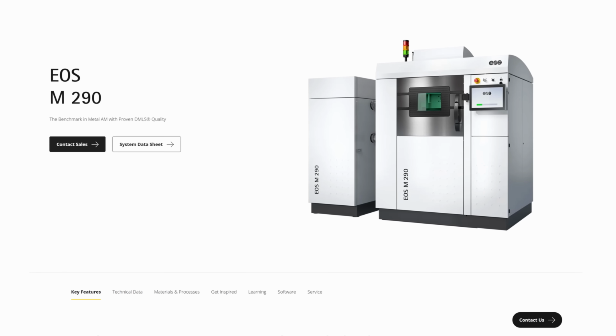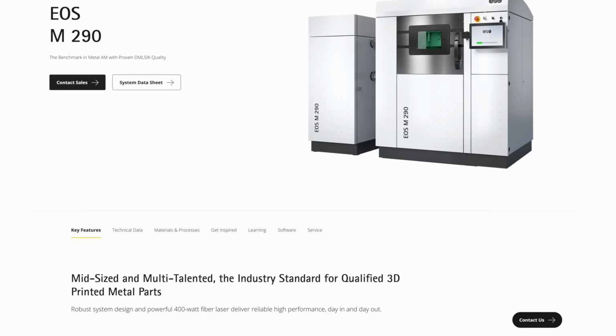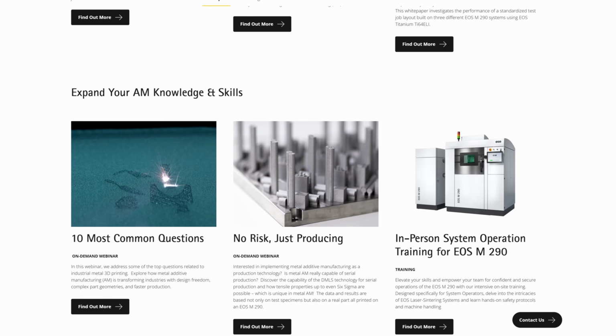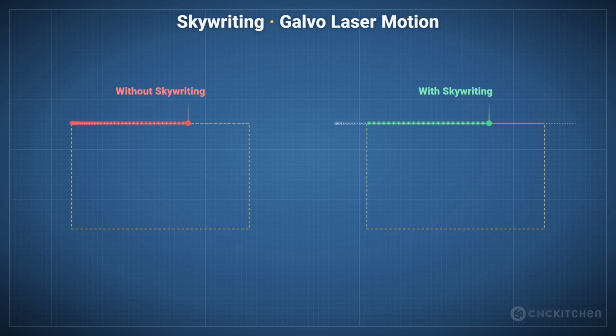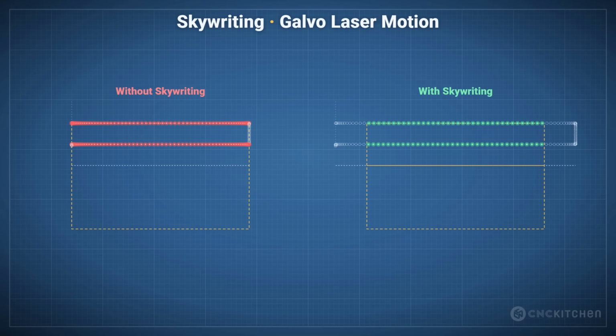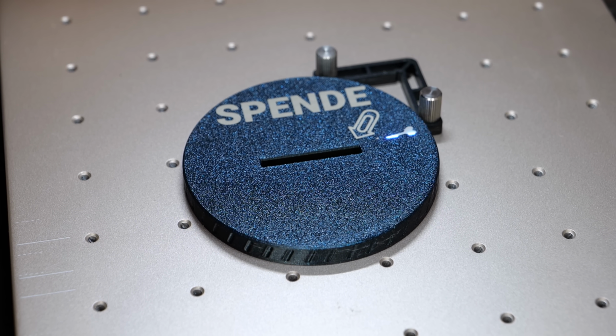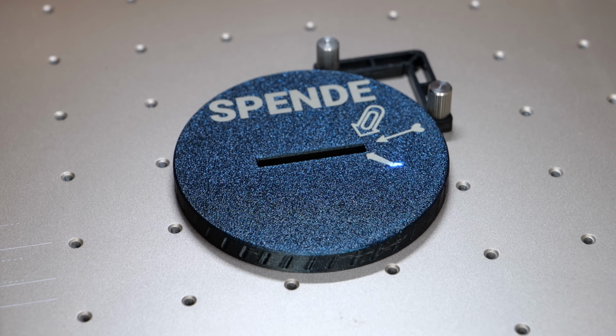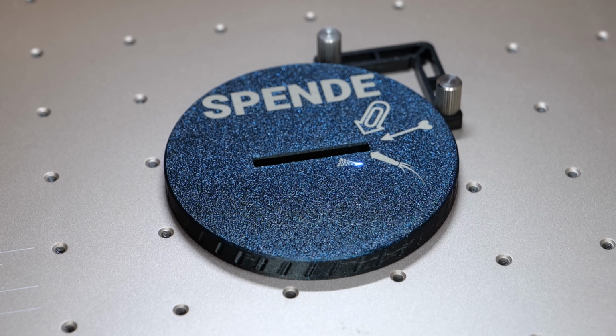From my time working in metal additive manufacturing, where we also used a laser that was steered by a galvo scanner to melt metal powder, I know a technique called skywriting. The idea is to extend the motion path beyond the actual marked area, so the laser only turns on once the scanner is already at constant speed inside the part and turns off again before decelerating. That gives you a much more uniform energy input. I'm honestly curious why something like this isn't implemented here. For most practical markings, it's probably not a huge issue, but under the microscope you can definitely see it, and also sometimes with your bare eyes.